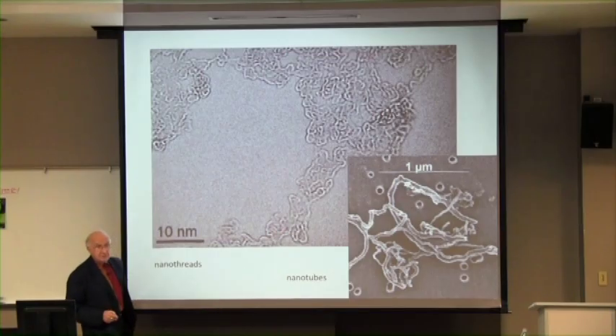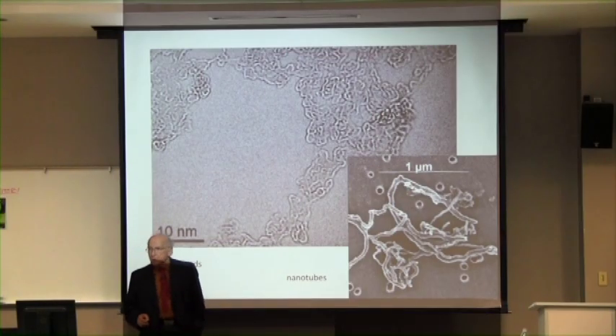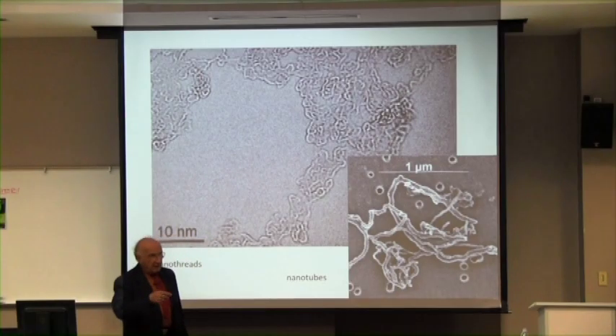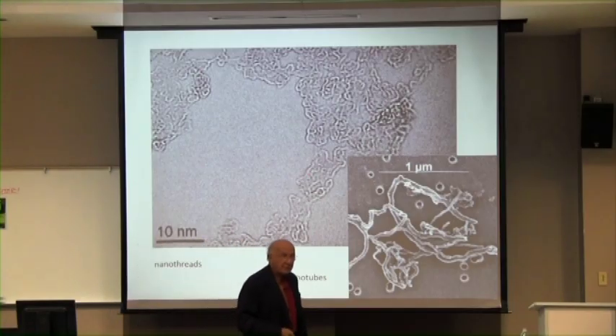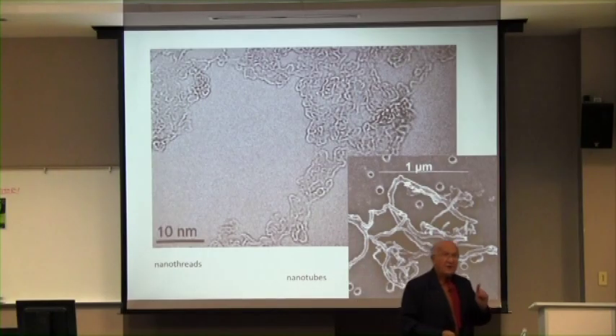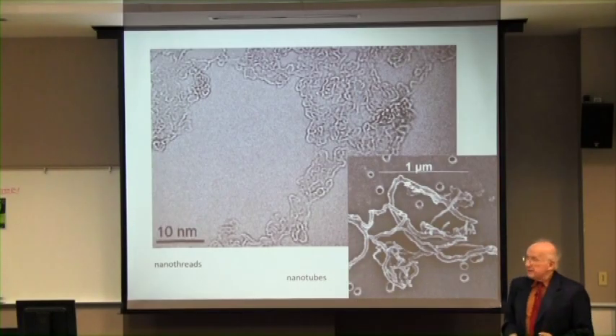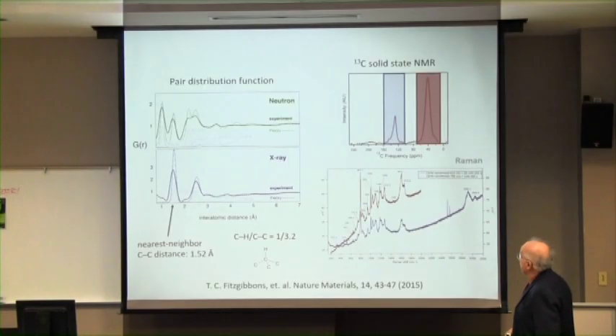These are nanotubes. Nanotubes are pure carbon, essentially curled up graphite, with very interesting properties. But look at the scale. This is 1 micron. 1 micron is 1,000 nanometers. So this is 10 nanometers. So you're down here. These things are down a factor of 40 to 100 from the typical nanotubes in thickness. So they're very thin. They're thin on a molecular scale, and that's about what a benzene ring is across once you add the van der Waals radius to it. So actually that was part of the story.